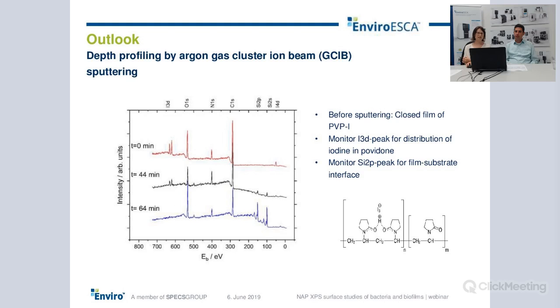After 64 minutes, you don't have any signal from iodine at all, and the dominating signal is from silicon. So here you see that there is a distribution of iodine in the film, and you can also monitor the film substrate interface.